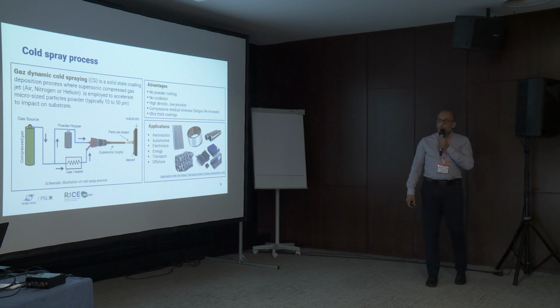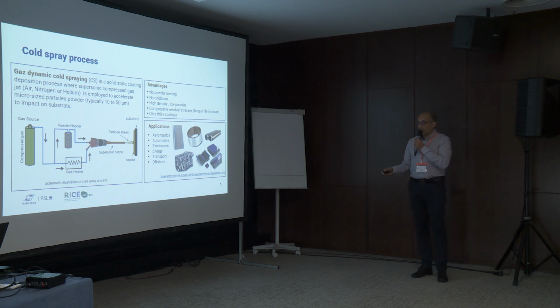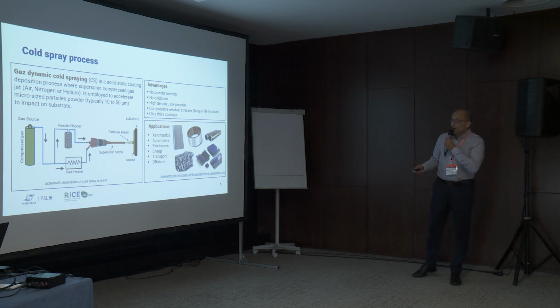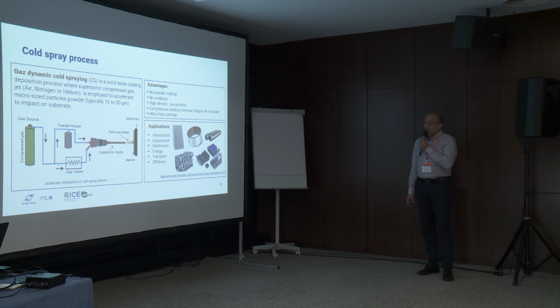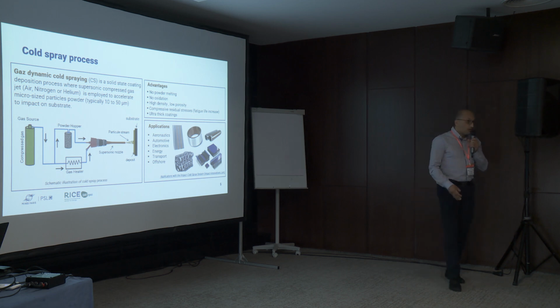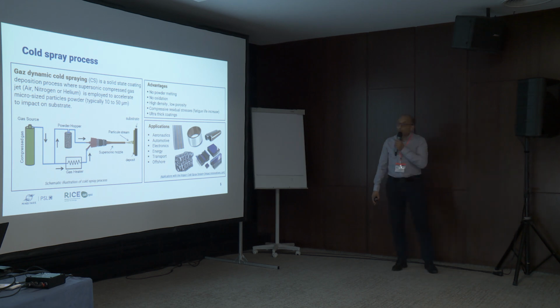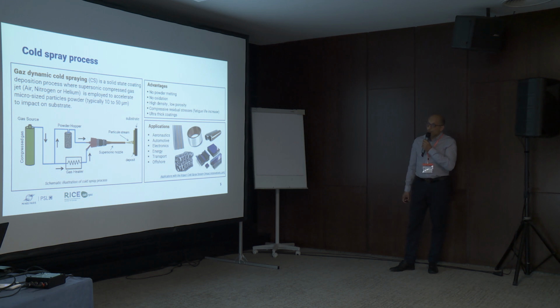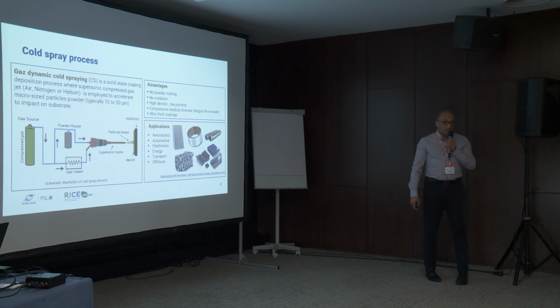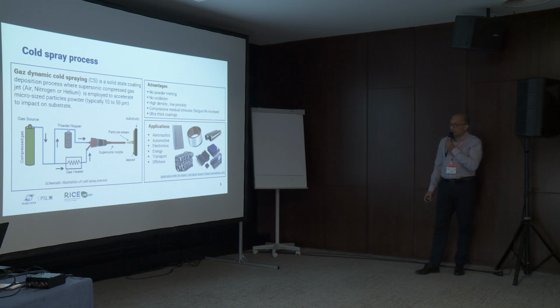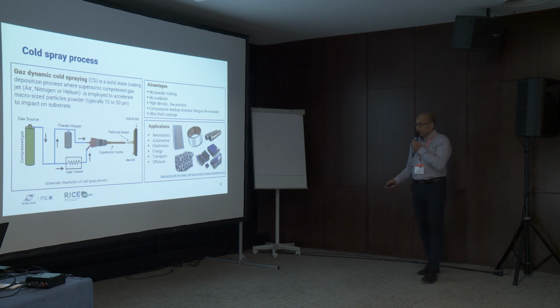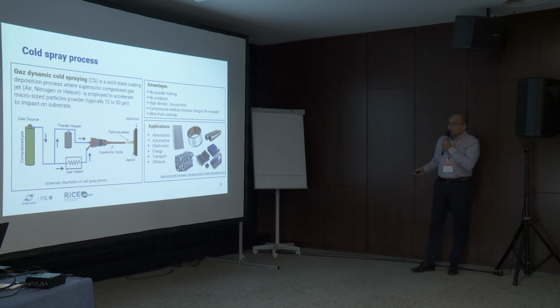So the cold spray process is a solid state coating deposition process where you have a supersonic nozzle here, with compressed gas using air, nitrogen or helium, and the powder is accelerated. The typical size of this powder is between 10 and 50 micron, and we have an impact of this particle on the substrate, and we get the coating like that. The main advantages are no powder melting, no oxidation, high density, low porosity. We get a better fatigue life using that compared to other kinds of additive manufacturing, because you have compressive residual stresses and ultra thick coatings.